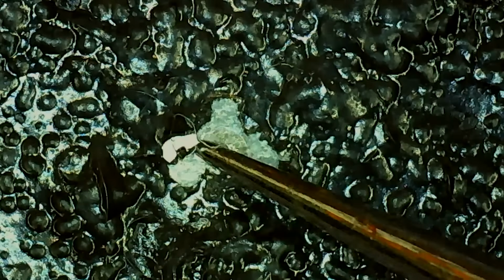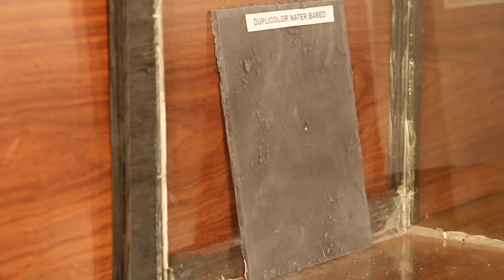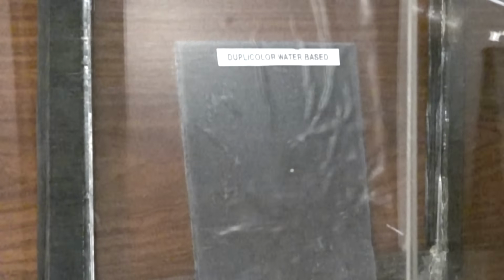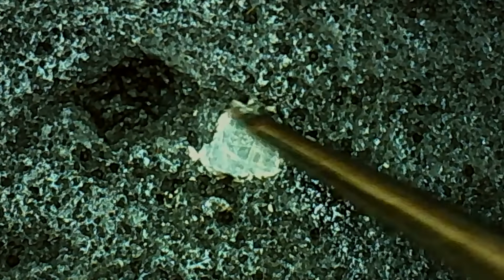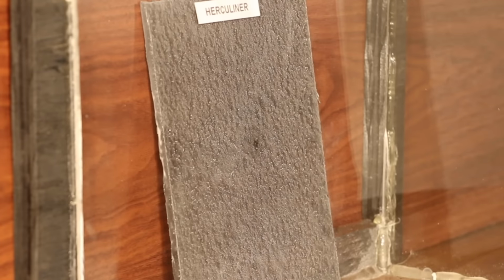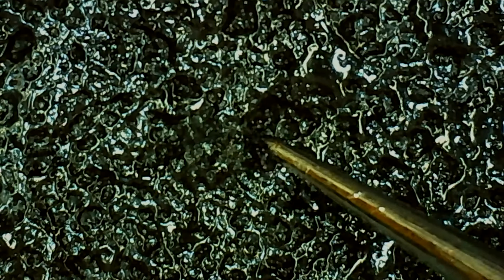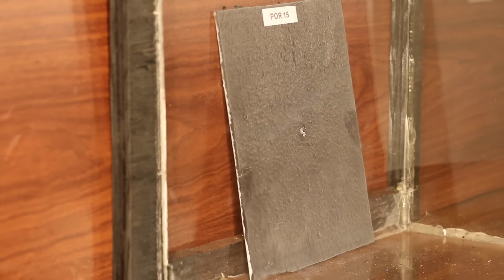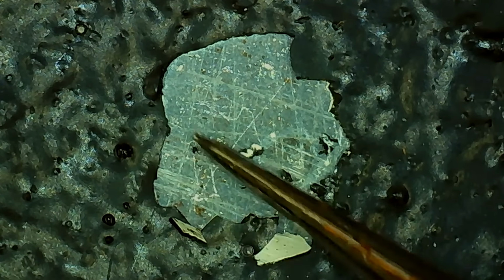The soft and rubbery characteristics of Flex Seal really helped it quite a bit in the colder temperature with only 2.16 millimeters of damaged area. The Raptor performed fairly well at 5.12 millimeters. The water-based Dupli-Color had a damaged area of 5.54 millimeters. Herculiner did the best yet. The steel ball did not fully penetrate the bed liner material. POR-15 had a damaged area of 9.74 millimeters.